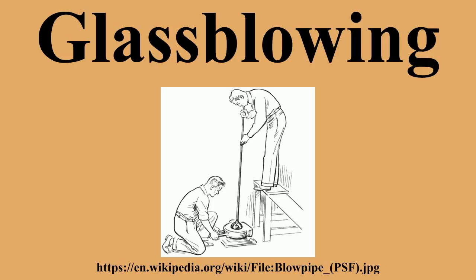The Roman leaf beaker, which is now on display in the J. Paul Getty Museum, was blown in a three-part mold decorated with the foliage relief frieze of 4 vertical plants. Meanwhile, Taylor and Hill tried to reproduce mold-blown vessels by using three-part molds made of different materials. The results suggested that metal, in particular bronze, molds are more effective in producing high-relief design on glass than plaster